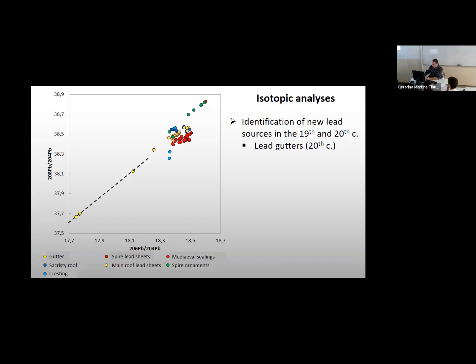And here you can see that some of the sources are clearly distinguishable. The lead gutters of the 20th century, as I spoke of before, are clearly aligned, clearly different from the rest. So this is new lead from a single mine, which is not being mixed with something else, apparently. Here, restored cresting from the 20th century, also the light blue ones, has a clearly different line, very different.